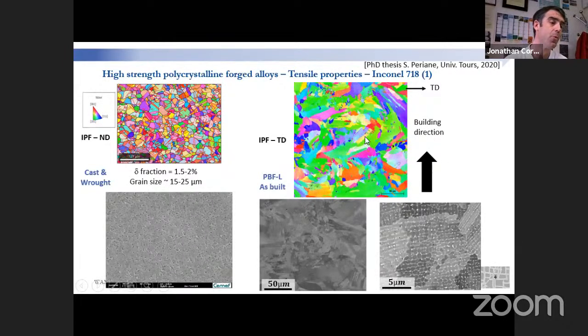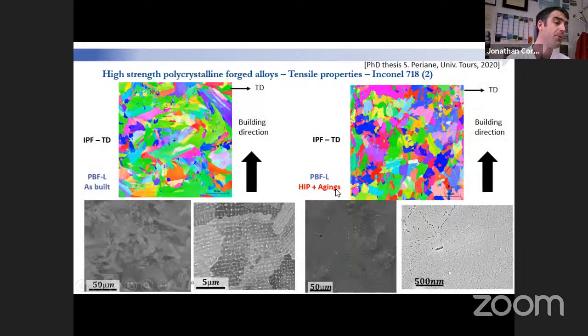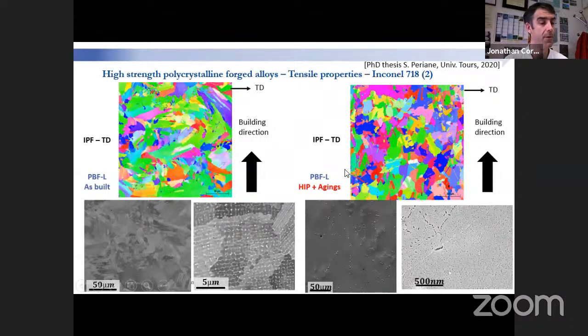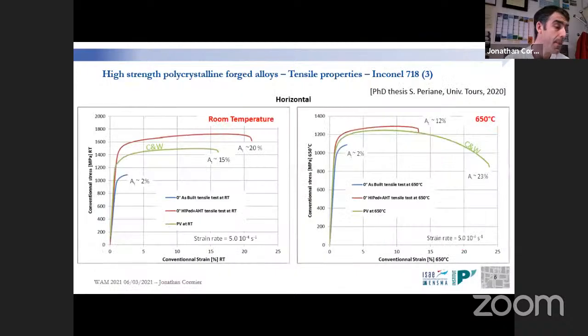So all this work has been done within the framework of the PhD thesis of Sassi Perian, in the framework of a collaboration with the University of Tours. And what we did also within this context, we wanted to use an optimized microstructure using HIPing. So we did HIP with an integrated HIP plus solution heat treatment, followed by aging to trigger the precipitation of the strengthening phases, so typically gamma prime, gamma double prime. Now, let's move on to the properties. First of all, tensile properties at room temperature and at 650 C. I'm just giving some typical curves. In fact, we have several results, at least 5 to 10 results each time. So you just have to take the picture, but we have several results to show this.